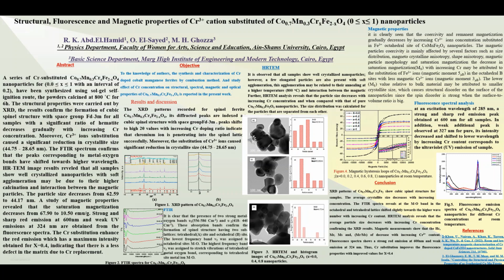From the XRD results, we found that the cubic spinel structure with space group Fd3m was formed for all samples, with a significant ratio of hematite, which decreased gradually by increasing chromium concentration. Moreover, the chromium ion substitution caused a significant reduction in crystallite size from 44.75 to 28.65 nanometers. FTIR spectrum confirms the formation of peaks corresponding to the metal-oxygen bond, which shifted to higher wavelengths.